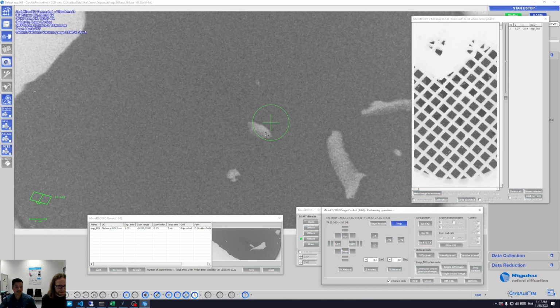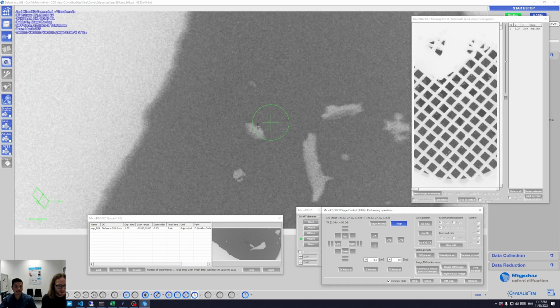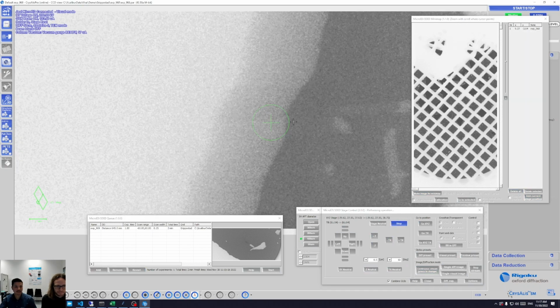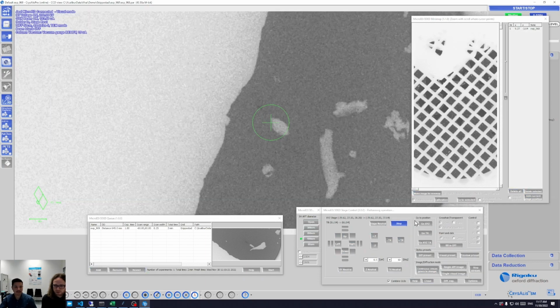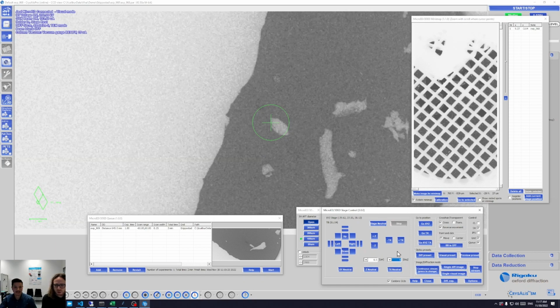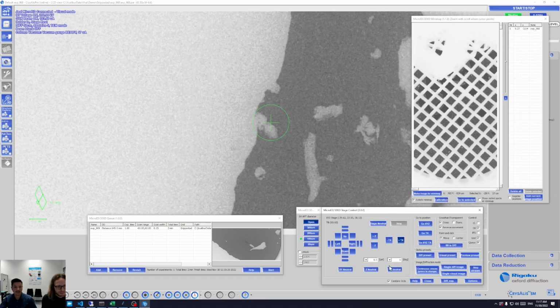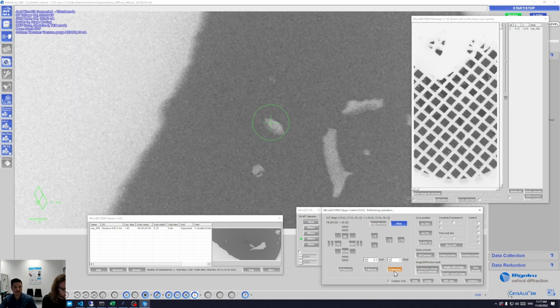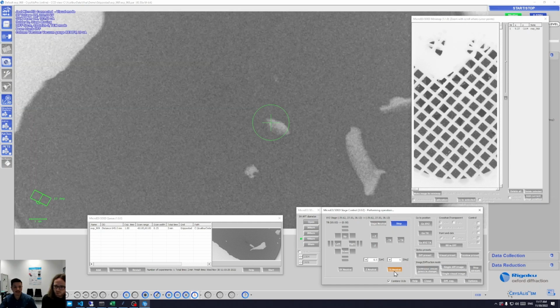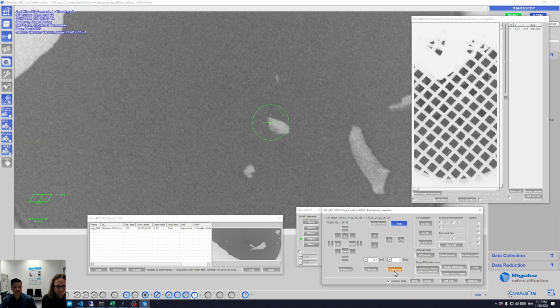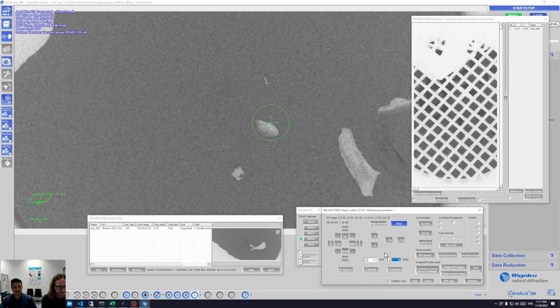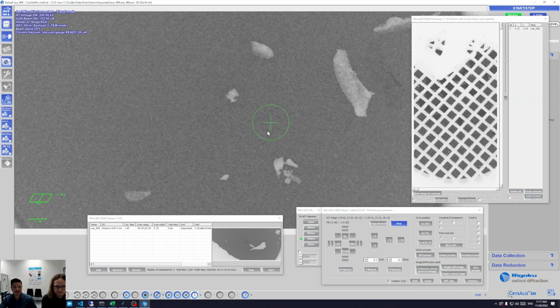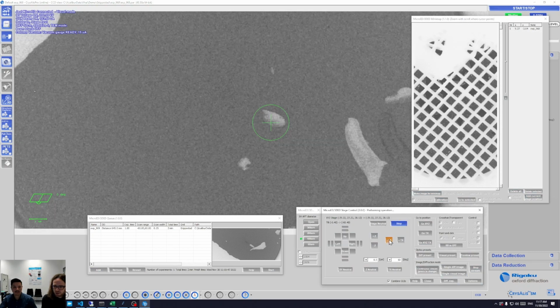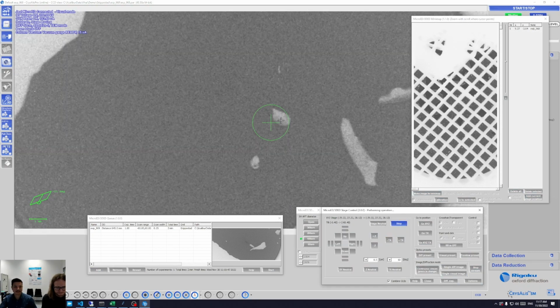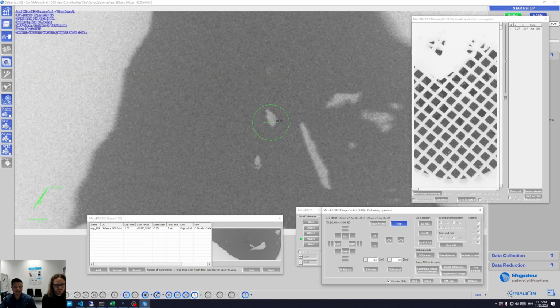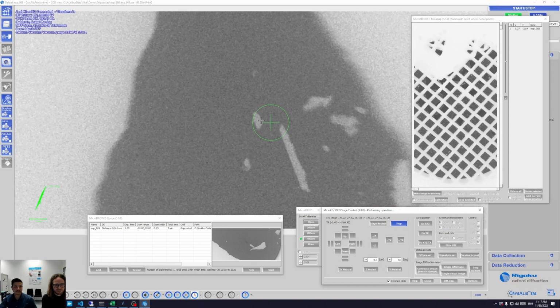So now again, the centering procedure. So we see here, we have a bit of a walk-off, so maybe we should recenter this a bit. If we went a bit further from the grid, you would notice that this walk-off would be larger, of course. What Kai is doing is symmetric centering, so checking it both at negative and positive values with respect to the perpendicular orientation of the grid to the beam. But as you see, it works quite nicely in both directions.